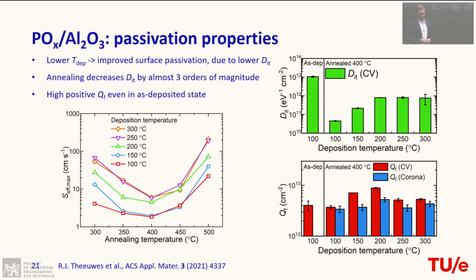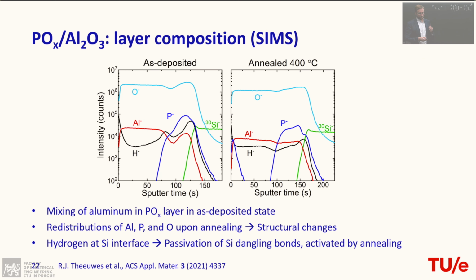And the good thing is that we have this high positive fixed charge density already immediately. So if you grow your layer stack, we have this high value. And if you do different things to your growth, it's not really manipulating this fixed charge density much. So that's a good thing, and it already makes it promising in that sense. If you can manage to get also low DIT values, then you probably have a good material for passivation.